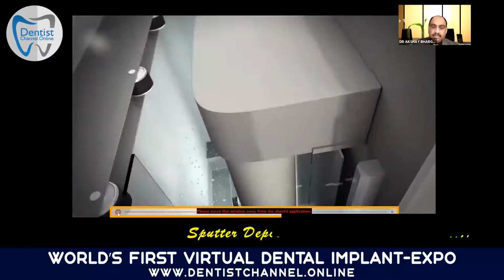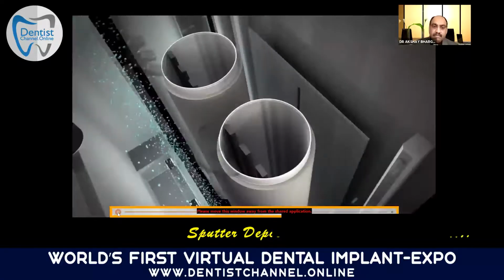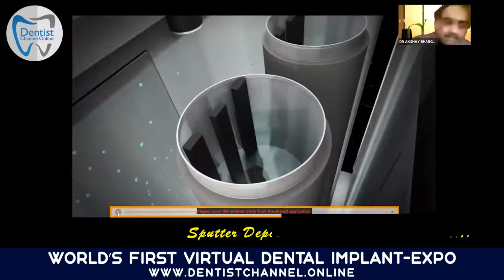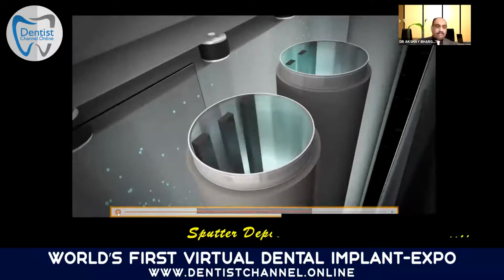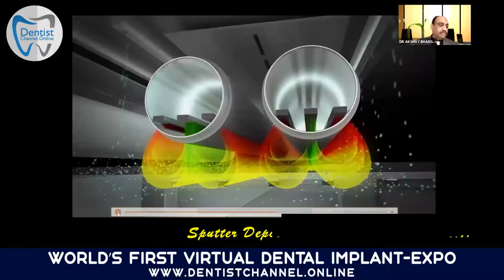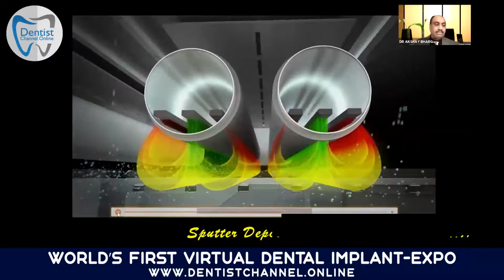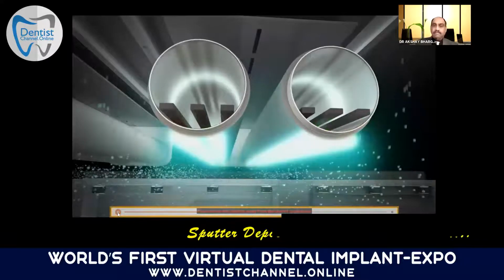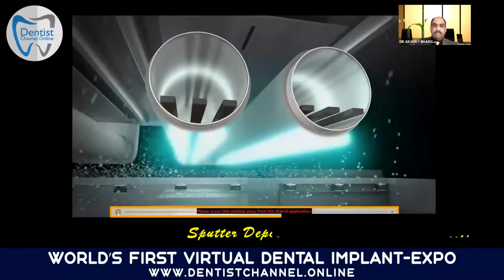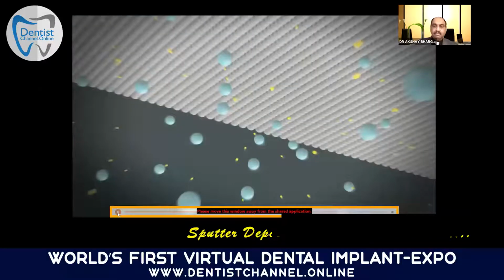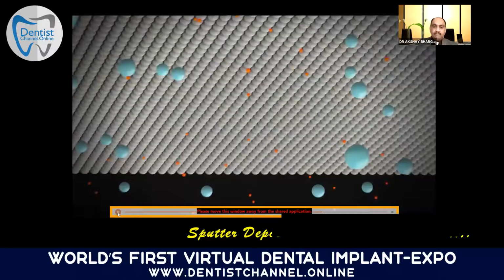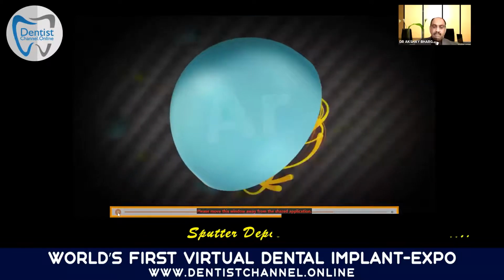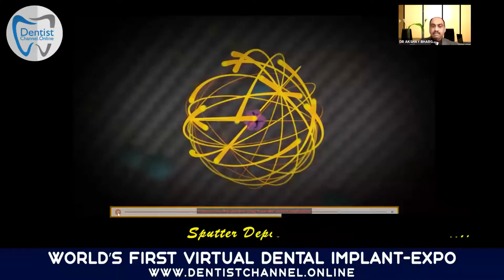Argon gas is introduced continuously to achieve a low-pressure argon atmosphere. A magnet array inside the cylindrical target generates a magnetic field. The target is filled with cooling water, which will dissipate the heat generated during the sputtering process. The targets are rotating so that the material will be utilized uniformly. A high voltage is applied to the molybdenum target and creates a plasma, which is concentrated along the magnetic field. The plasma consists of argon atoms, positively charged argon ions, and free electrons.